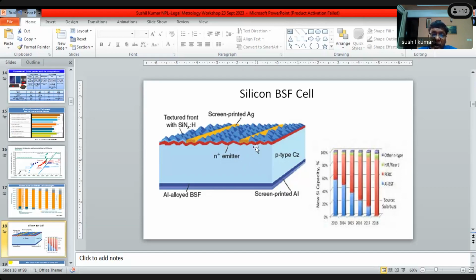But to have more absorption you should have an anti-reflection coating. To minimize the reflection losses, texturing is performed and the surface area also increases so that you can have more absorption there. Contacts are made, the top contact and the bottom contact. With screen printing, silver is used, and at the back screen printed aluminum is used.